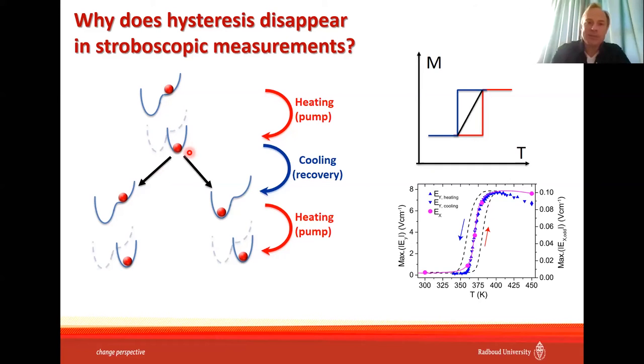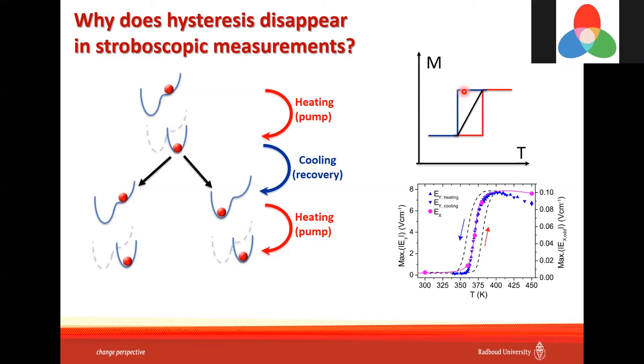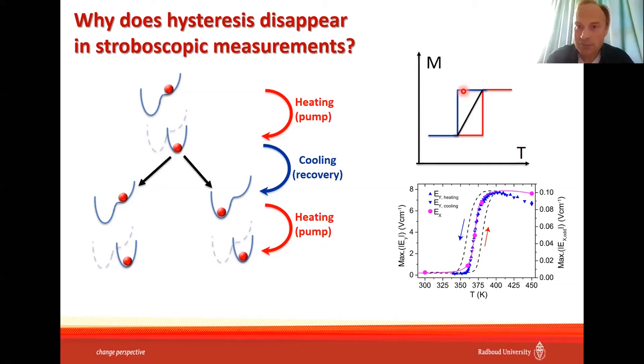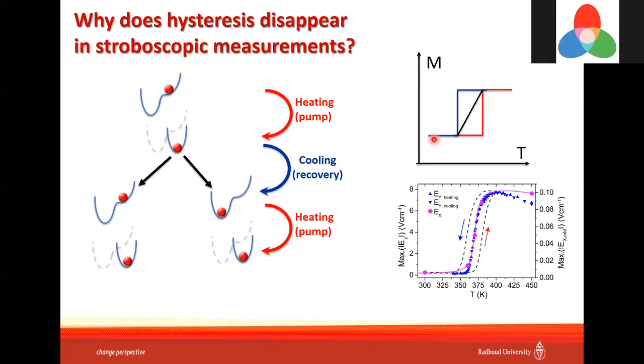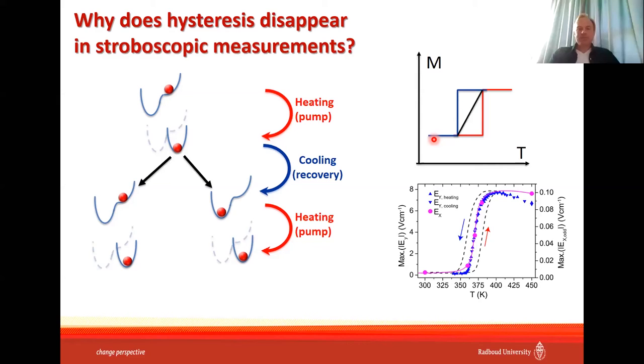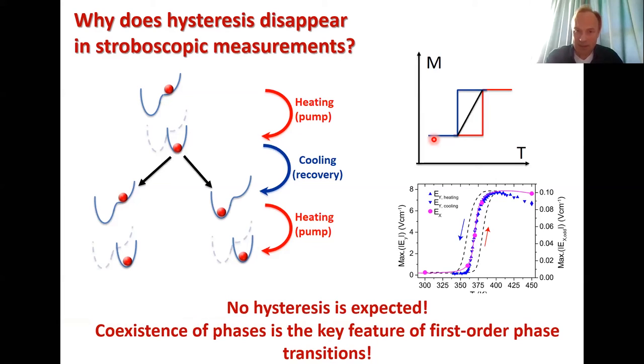So imagine it's not temperature, imagine it's magnetic field. You switch once with magnetic field, and then you want to restore the initial state. So you have to apply a magnetic field large enough such that the second state doesn't exist anymore. You are not in temperature hysteresis, but in field hysteresis. Because as long as you stay in the field hysteresis, you have uncertainty about the state. It could be one of the two states where the system eventually relaxes to. Okay, right? Thank you. So if you're sitting here, you can sit here infinitely long, in theory. Even though this state is less energetically favorable, you really have to go here to make sure that you initialize the initial state. Good. So our conclusion is no hysteresis is expected here.